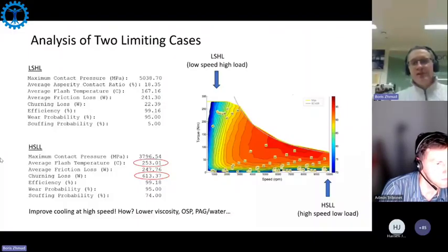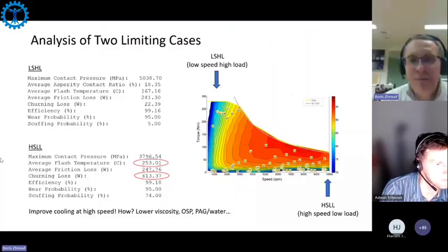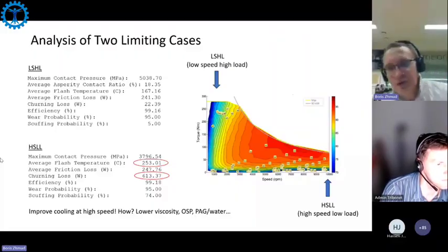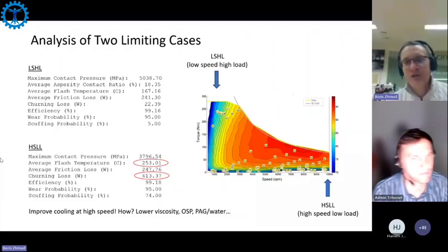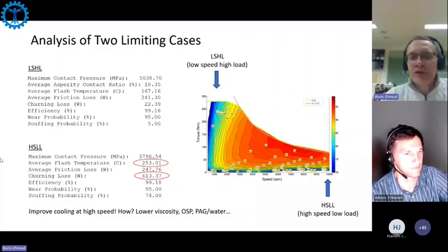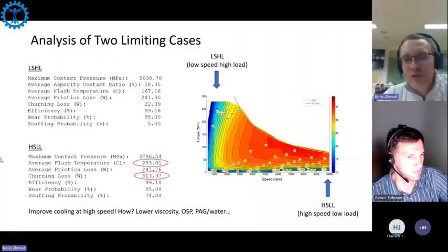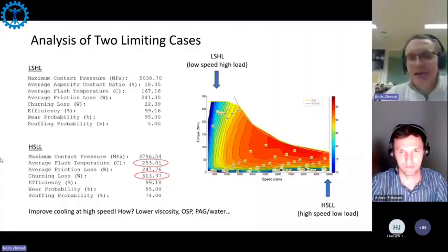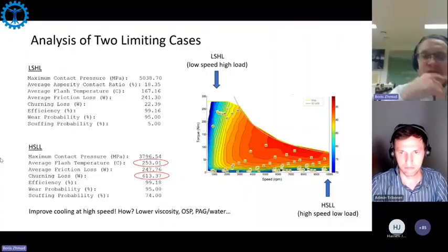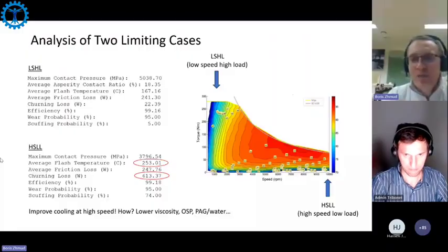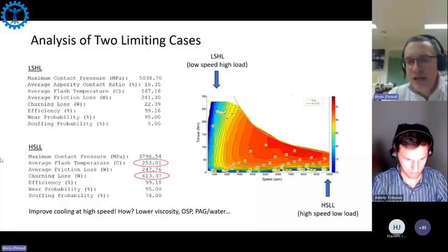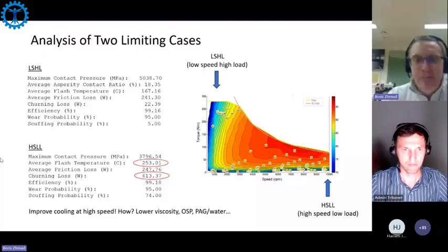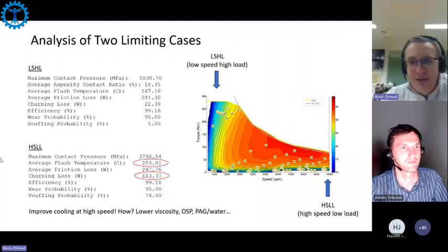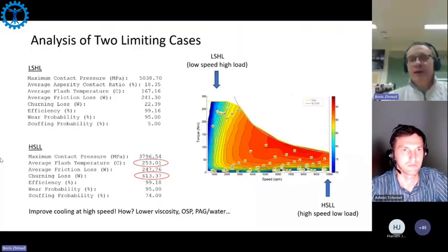And when you get such high churning losses, you will of course have an increase in temperature of your gearbox, because you also transmit higher power through it, plus a lot of churning losses. So you would need to improve cooling. And what do you do to improve cooling? You can use fluids with better heat capacity. For example, you can go from hydrocarbon bases to esters or polyethers. And to get the ultimate effect, you can go to polyalkylene glycol water formulations, as I mentioned before.